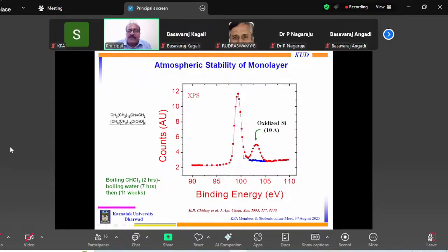What you see here is, once you take silicon, create a clean condition, and leave it just for a few days, you can see the oxidation peak that is coming out. And here it is a typical spectrum recorded by these people. What they claim is that within a few days, silicon will have a silicon oxide layer of 10 angstrom, and it is a self-limiting process. Probably it will go to 10, 50, 100, then it will limit, and then it will act as a protective layer. There will not be any further oxidation.